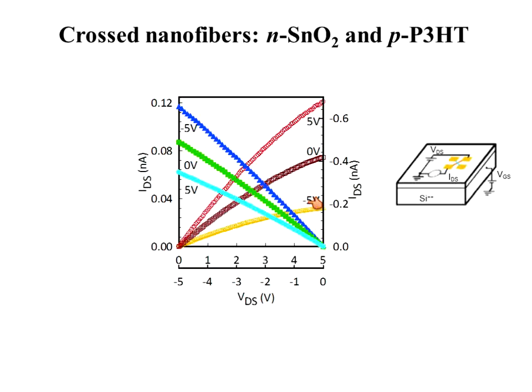On the other hand, if you were to look at P3HT, you would go to these three curves over here, which, since it's p-doped, should be done in the third quadrant. And then you can see that for negative gate voltages, you have a higher current compared to positive gate voltage. So P3HT is p-type. So you have p-type P3HT, n-type SnO2, and let's see what happens when you go across